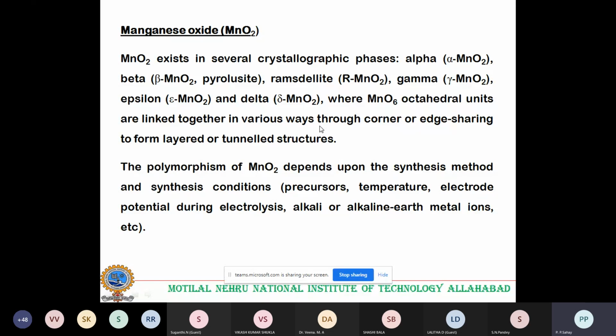Now, one question will come to your mind. Normally, with anything, there should be one crystallographic phase. What happens in the case of manganese oxide? The polymorphism of the manganese oxide depends upon the synthesis method, how you prepare the manganese oxide. Not only the synthesis method, it also depends upon synthesis conditions, like the precursor which you are using, the temperature, electrode potential, and so on. There are different synthesis process parameters that will influence the crystallographic phases of MnO2.